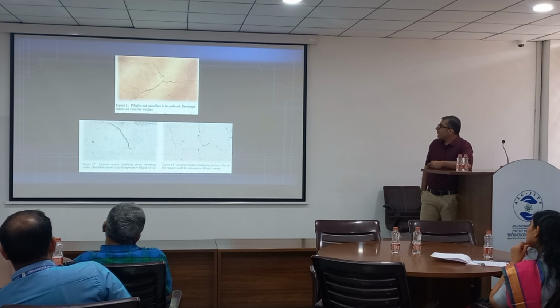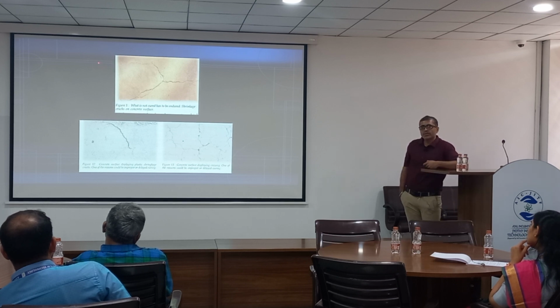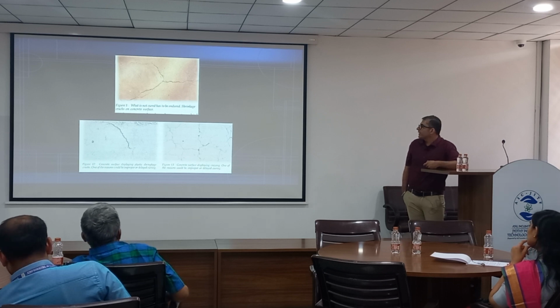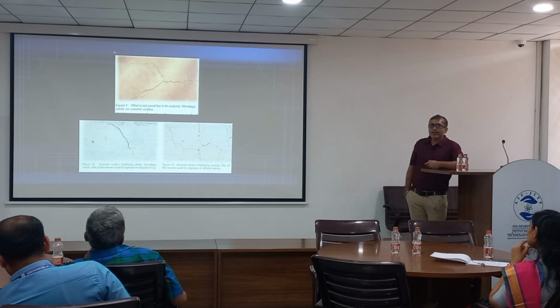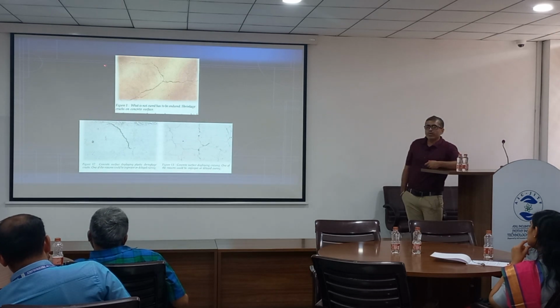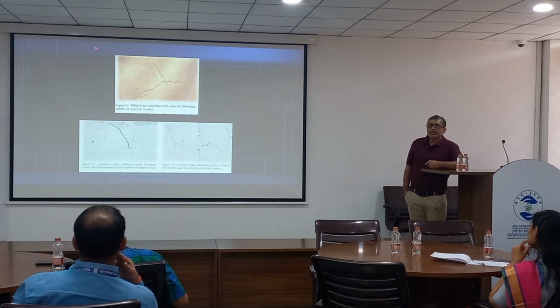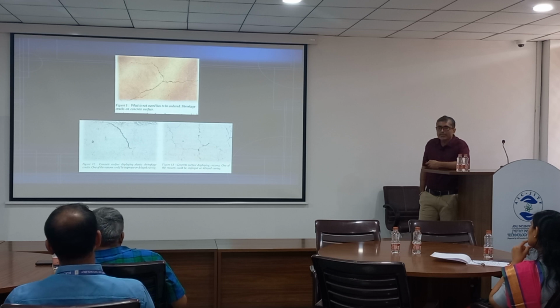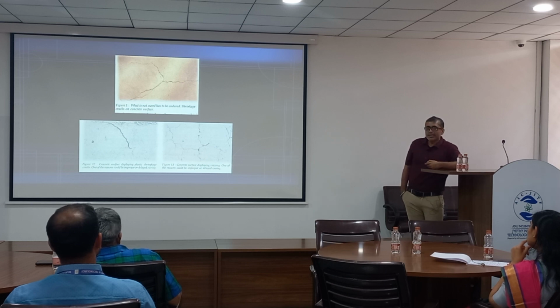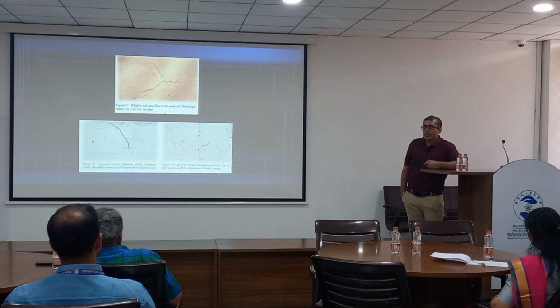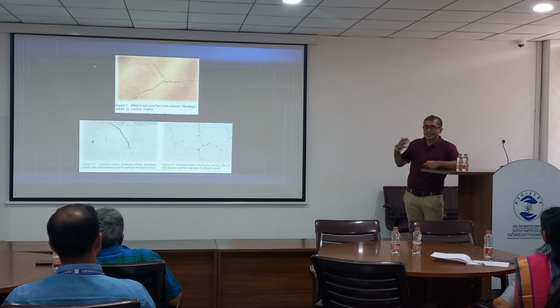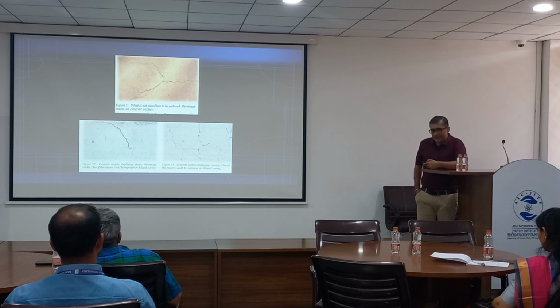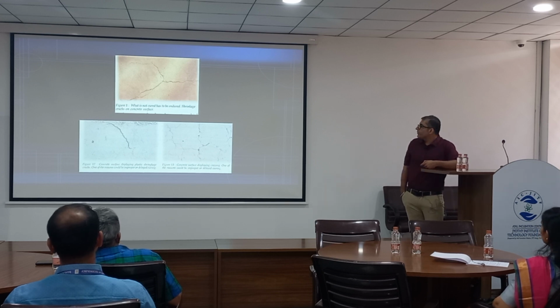These are very common shrinkage cracks which occur in slabs. Once the concreting has been carried out for these slabs, the shrinkage cracks tend to occur. If proper curing can be ensured, then the intensity at which the shrinkage cracks form can be greatly reduced. Please understand that shrinkage cannot be controlled completely. Why? Because as the hydration process starts, the water starts getting converted, so obviously there will be some change in the volume, because of which shrinkage can happen. So you have to ensure that the curing process is continuous.